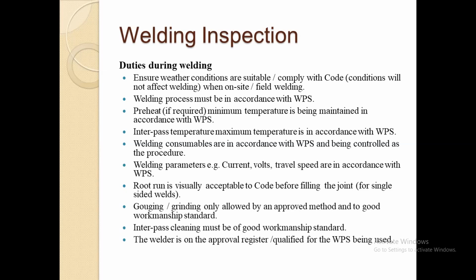So it's not what a welder thinks he should use based on his experience, but what the WPS specified: this is the range you should be operating in for this size electrode. So that is what has to be used. The inspector also has to check the root run to make sure that it is acceptable before the weld is continued. Gouging and grinding have to be checked by the inspector as well to make sure that the proper workmanship standard is maintained. Interpass cleaning must be checked, and the inspector also has to make sure that whichever welder is being used is registered and qualified for the WPS that is being used.